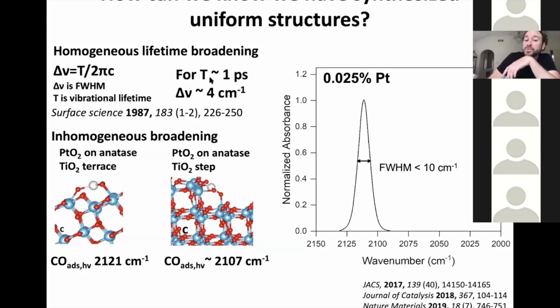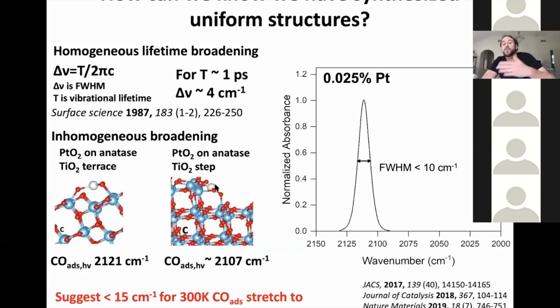And if you include the homogeneous broadening of each one of these, you would have a band that's maybe something like 20 inverse centimeters wide, which is clearly much broader than this. And so likely we only have one of these species. So what we always suggest is having less than about 15 inverse centimeters at 300 Kelvin for the CO stretch as a good way to justify that you should move on and then try to identify the structure of this site. If it's broader than this, likely you have multiple different species, and so structural assignment will be challenging.